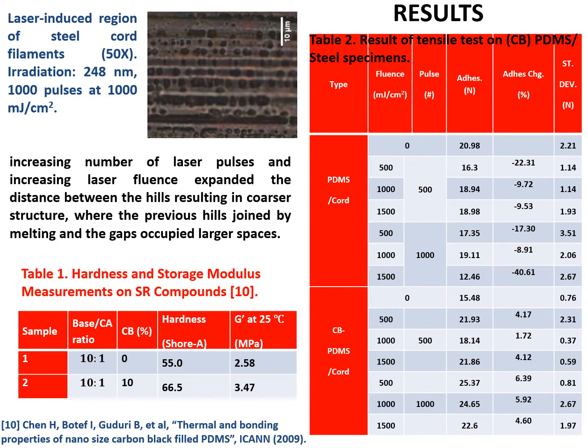The table on the lower left shows the effect of adding carbon black in 10% proportion. You can see that both the Shore A hardness and the storage modulus G prime at room temperature increase when we add the carbon black reinforcement. The table on the right shows the increase in adhesion when we do the pull-out test. The lower part is with the carbon black PDMS cord composite, which gave us well-behaved results. You can clearly see when we go from 500 pulses to 1,000 pulses, the adhesion goes from about 18 newtons pull-out force to almost 25 newtons pull-out force. So there's a clear increase in the adhesion, and the same thing occurs with the increase in fluence.